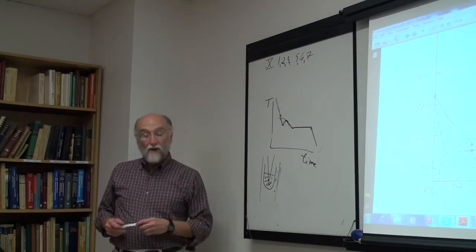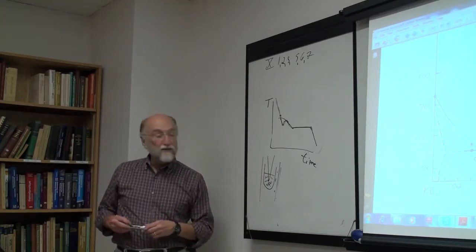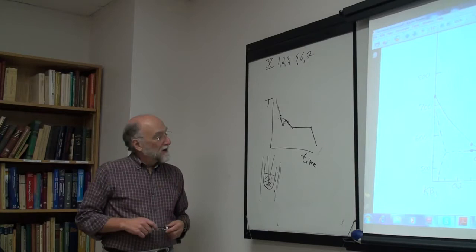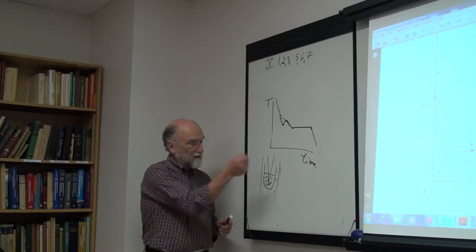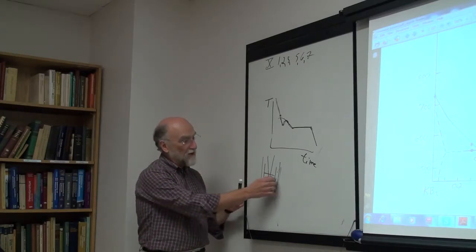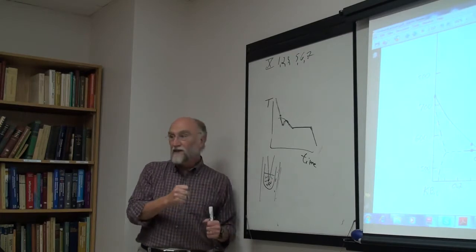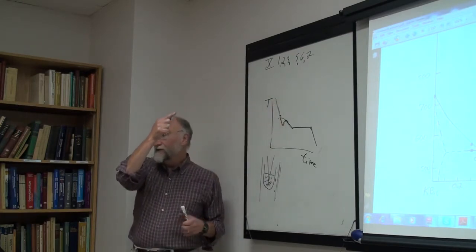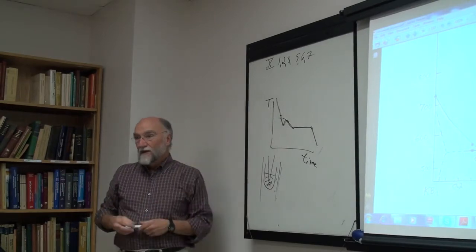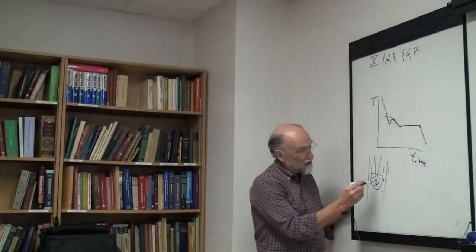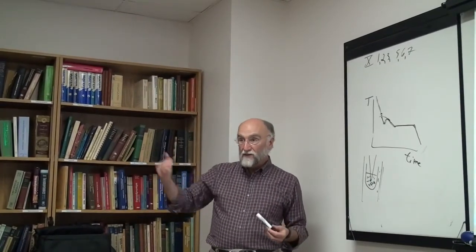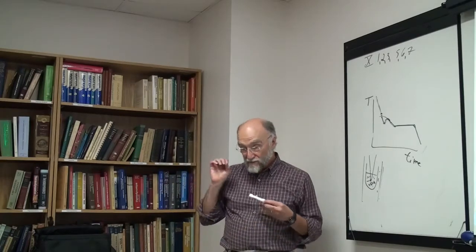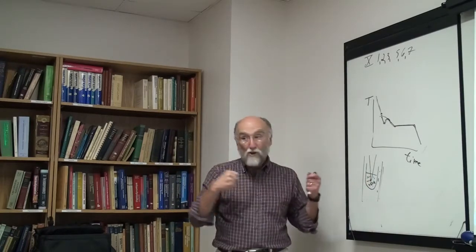But you also try to favor nucleation. One way to do that might be to put some nucleation sites in there, like a little bit of sand. But what is found, and there's even been controversy today, is that if you shock the thing, if you give it a good whack, or agitate the sample, suddenly it nucleates, and the temperature shoots back up. The theory of that is that you're initiating shock waves locally, which raises the pressure locally, and higher pressure favors the formation of the solid phase. So just locally in a very small region, you form a nucleus by the high pressure, and then that nucleus grows.